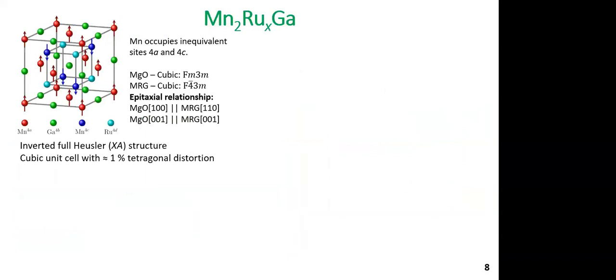So manganese ruthenium gallium thin films are grown by DC magnetron sputtering on single crystal MgO (100) substrates. The films crystallize in the inverted Heusler structure. Biaxial substrate strain induces a tetragonal distortion of about 1%, and hence the net moment exhibits perpendicular magnetic anisotropy.